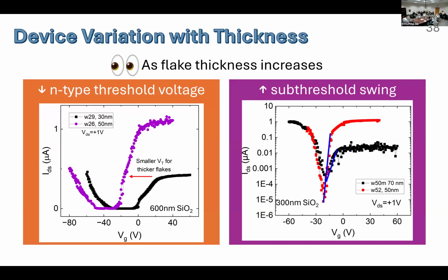And I can actually use that to explain the differences in the device variation with thickness. One of the things that we notice is that for thinner flakes, we see an increase in the threshold voltage from the left to the right. We also see an increase in the subthreshold swing for thicker flakes.